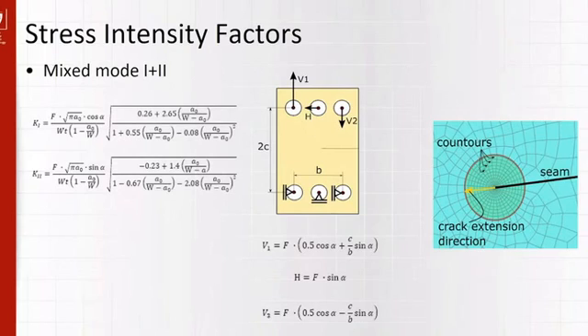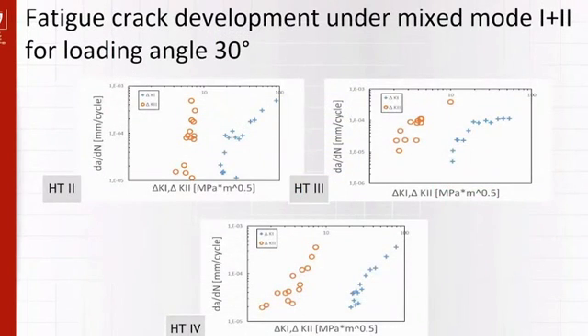In order to receive K1 and K2 values, a numerical analysis was conducted based on what you see in the middle of the slide, using the contour integral method, which focuses on small jumps of the crack length close to the crack tip. The visual of this method is presented on the right-hand side. Based on the physical and numerical tests, charts were created for K1 and K2 influence and the crack growth rate for all three heat treatments.